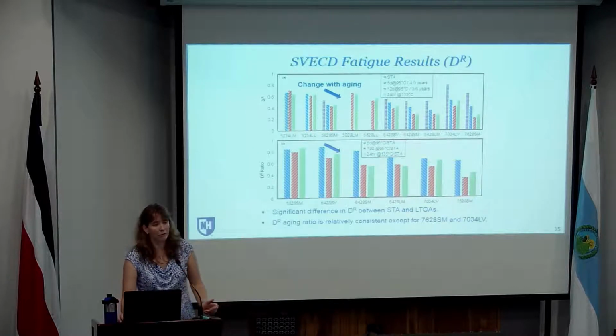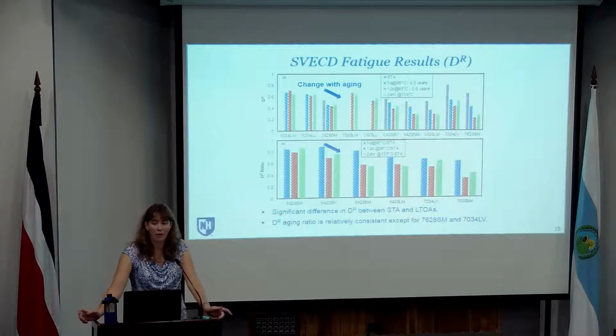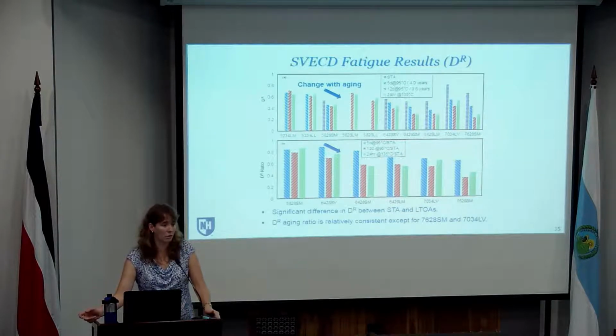So you can see, in general, we're seeing a decrease in that DR value with aging, not unexpected, right? What we'd anticipate happening as the material ages, it becomes more susceptible to cracking. Now the one thing that is interesting here is, remember when we were looking at the viscoelastic material response, the 12 days and the 24 hours were pretty much the same, and they were statistically the same for that viscoelastic response. When we start looking at the fatigue response, that's no longer true. So when we start to look at a test that actually produces damage in the material, we're seeing a difference in the response from those two different aging protocols.